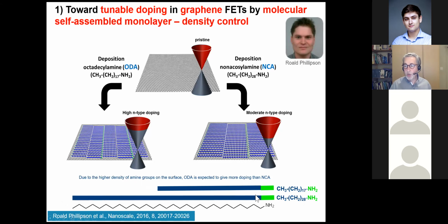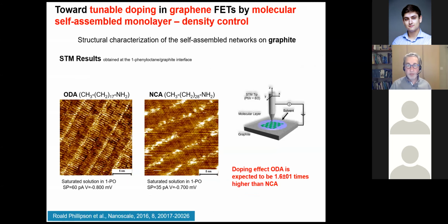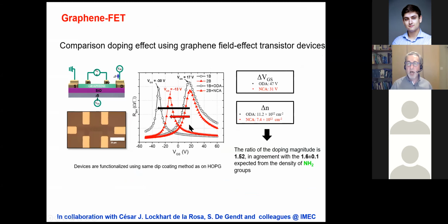And of course, the long molecule should have a lower density of amino groups on the surface than the short molecule. Well, we can use STM, AFM to visualize the structure that these linear molecules form on the substrate. And indeed, they form this kind of, from our perspective, straightforward self-assembled molecular networks where they organize in rows.